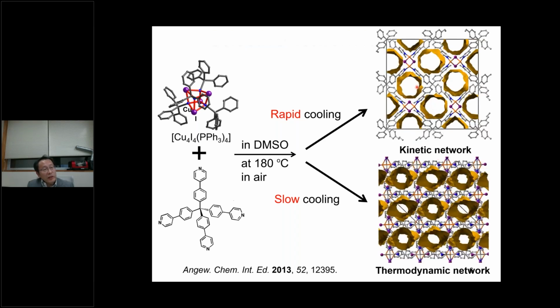First of all, let me show the crystal structure. In the kinetic product case, the feature is that you can generate an interactive site, this red circle. This one is actually a bridging iodide atom. This iodide is facing this pore. However, in the thermodynamic network case, this interactive site is covered by a ligand. So this iodide cannot face the void. So using kinetic assembly, you can generate an interactive site in a pore. That's why we pay attention to this kinetic network.